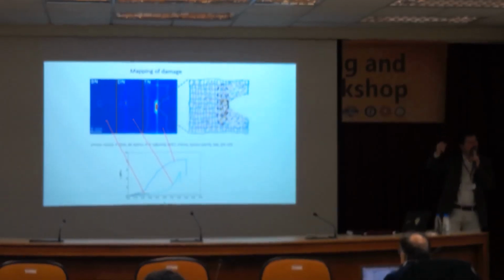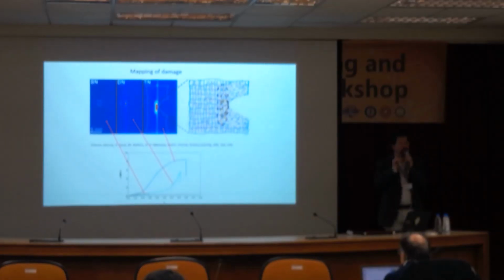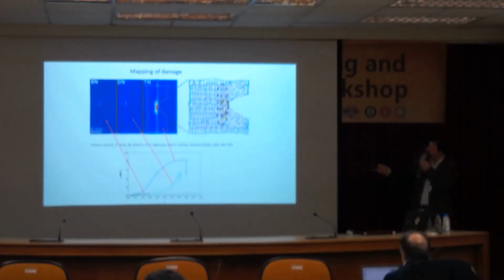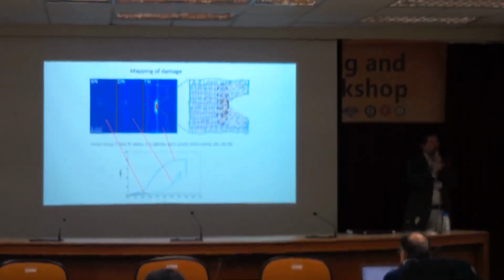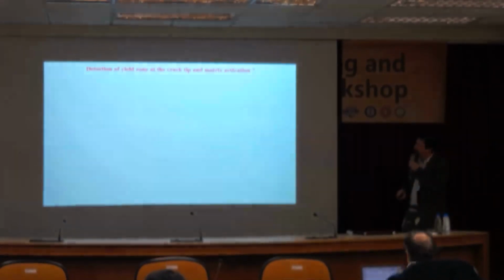Now, if we get to the double here, this is a slightly pre-stretched network. It actually sees strain stiffening, but at breakage point, there is actually some bond breakage. We don't see any bond breakage in uniaxial extension for this material, but at the crack tip we do. So this is an important point of fracture, is that you may not see any damage in your material when you stretch it, but when you actually break it, you always have some damage in front. And this is this tougher one here that has very large energy dissipation, indeed has a very large volume of dissipation. So with this particular experiment, we could really prove how this bond breakage was directly instrumental for toughness.